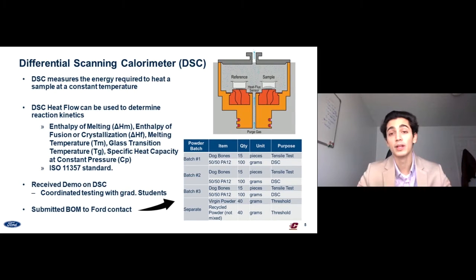So going a little bit more into the DSC, essentially what it is, it just measures the energy that's required to heat a sample at a constant temperature. And how it does this is, as you can see on the right side, we have a reference pan and a sample pan. The sample pan has our powder, and the reference pan is going to be empty. When it goes through the heat cycles and the temperature ramps, it will measure the difference.